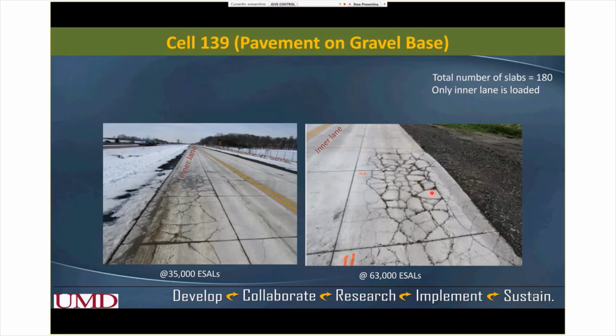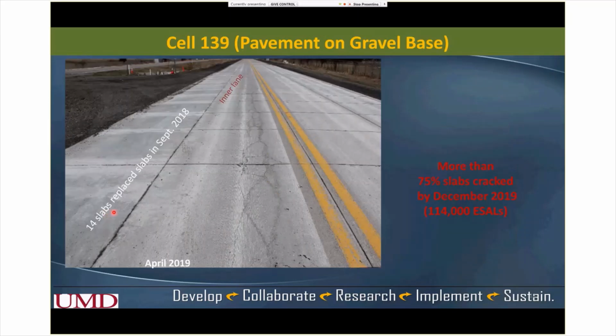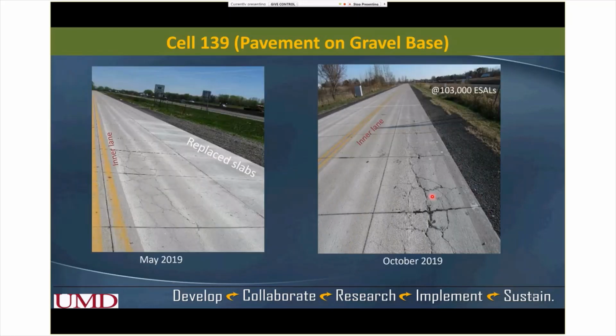So in September 2018, those slabs which were broken or shattered were replaced, 14 slabs. And then when the distress survey was conducted in December 2019, after 114,000 ESALs, it was found that more than 75% of the slabs of these cells are cracked. So these are two additional pictures collected in May 2019 and October 2019, and there are a lot of cracks in these cells.